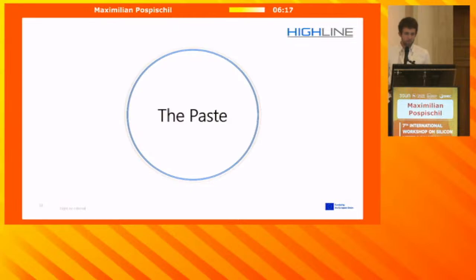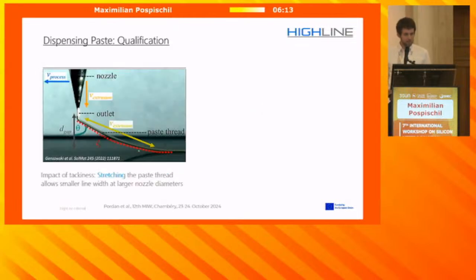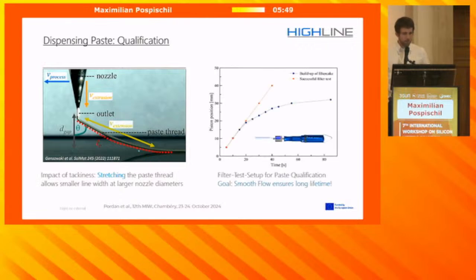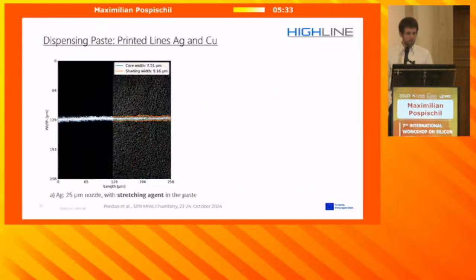And then, what we also need is a paste. Now I'll show you how to do small lines with larger nozzles, or let's say smaller lines with larger particles that require larger nozzles. As shown by Katharina, who was a former PhD student at Fraunhofer ISE, the stretching of the paste works very well with dispensing. And the second thing we want to do with the paste is qualify it, and for that we set up a little filter setup. We make sure that there's no buildup of a filter cake, because that ensures that we have a long lifetime of our components. And what we achieved here with this feature, you see here a 25 micron nozzle, but with some stretching agent added to a silver paste, we end up at like 7.5, or let's say below 10 microns.